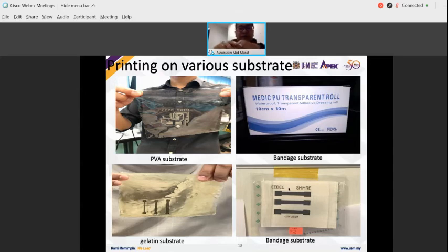So that is some of the various substrates that we have done, and commonly we also print on polymer substrates. But the polymer is only bendable, it cannot stretch. So this is a few substrates that we focus on in our group. We control the ink formulation in terms of the wettability, the viscosities, the mix ratios, and then the particles and also the polymers. And then we tested a few substrates that can be applicable for biosensors.